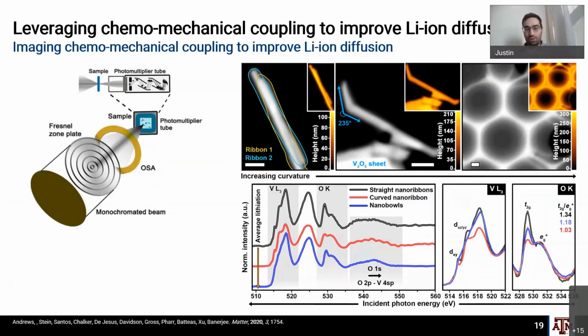Looking at these, what we're able to show is the curvature that's inherent in these materials. Here I've got a perfectly straight V2O5 nanowire, a bent V2O5 nanowire that's strained and curved at this particular point, and this inverse opal structure. These are transmission optical density images, and the corresponding integrated spectra, averaged across the entire images, are shown below. The black spectrum corresponds to the straight nanowire, the red to the bent nanowire, and the blue to the inverse opal.